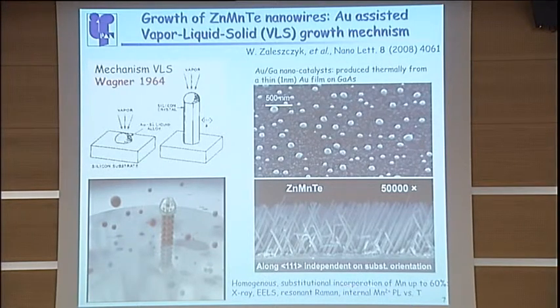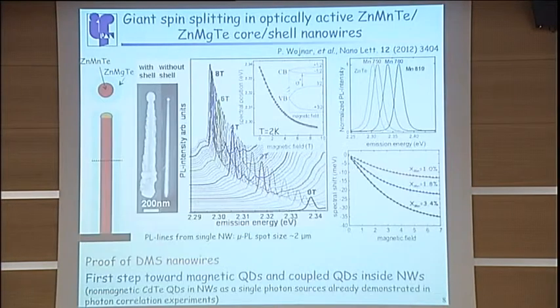Now we have shown that it is in fact possible to incorporate up to 60% of manganese, and we have shown this by electron energy loss spectroscopy, resonant Raman scattering, and studies of manganese internal transition. But of course, just to demonstrate that they are really diluted magnetic semiconductors, you have to prove that they have a very strong enhancement of spin properties. So this is an example of such a study.